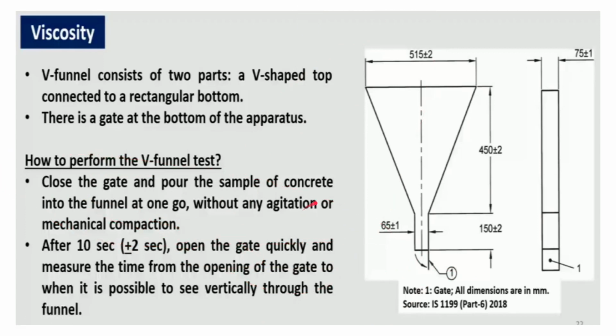As we have seen, in all the tests there is no use of any agitation, compaction or vibration. After 10 seconds plus minus 2, open the gate quickly and measure the time from the opening of the gate to when it is possible to see vertically through the funnel.